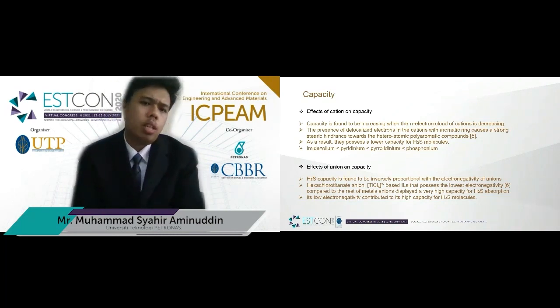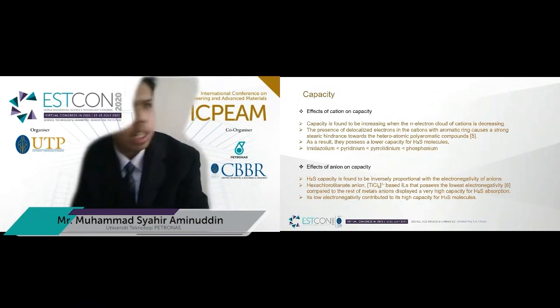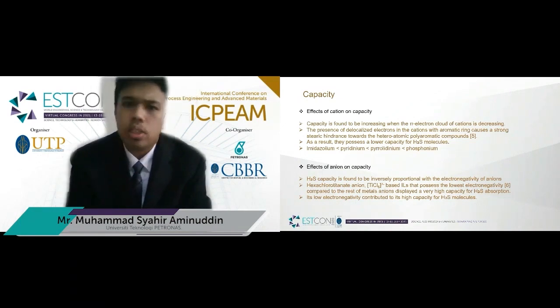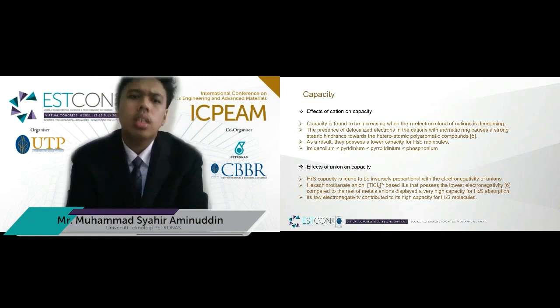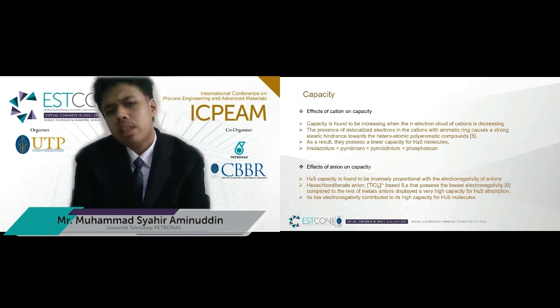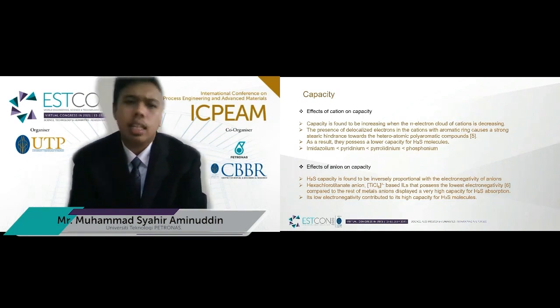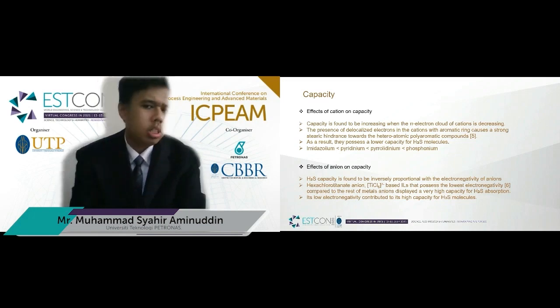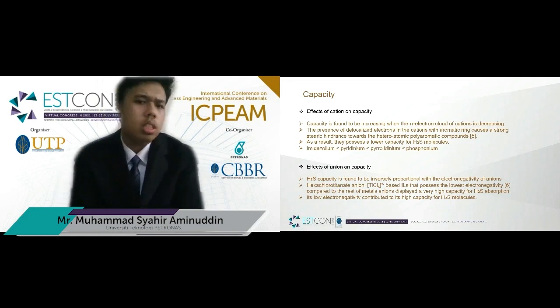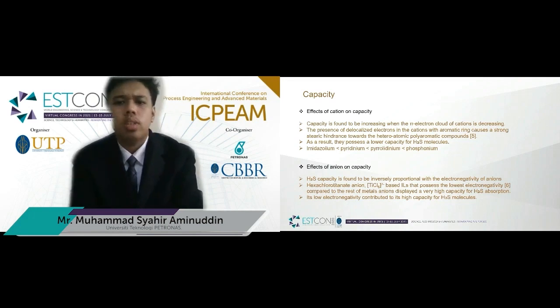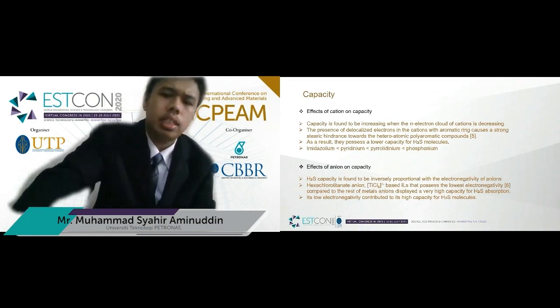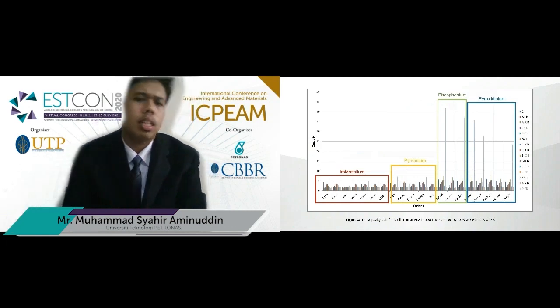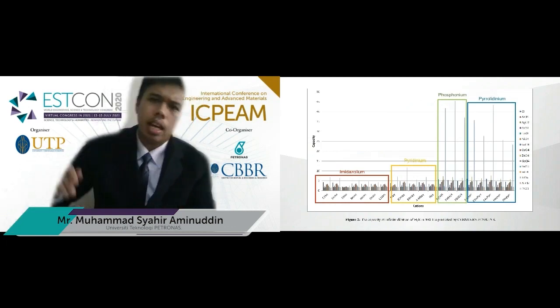Capacity is also affected by anions. The hydrogen sulfide capacity is found to be inversely proportional to the electronegativity of anions. This is because, for example, the hexachlorotitanate anion TiCl6-based ILs, which possess the lowest electronegativity compared to the rest of the metal anions in the screening process, displayed a very high capacity for hydrogen sulfide absorption. This is because its low electronegativity has contributed to its high capacity for H2S molecules. This is the graph for capacity for all 300 ILs.